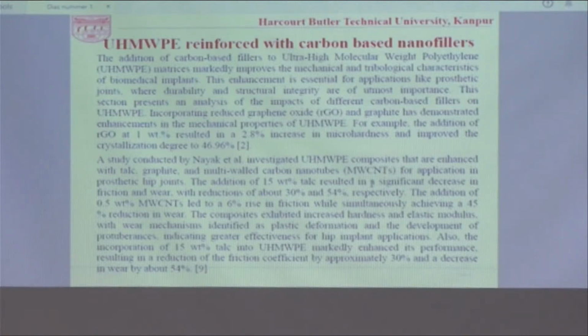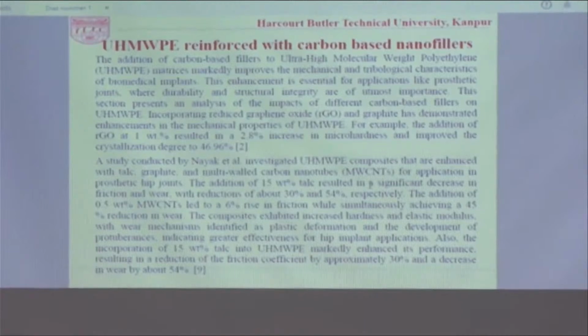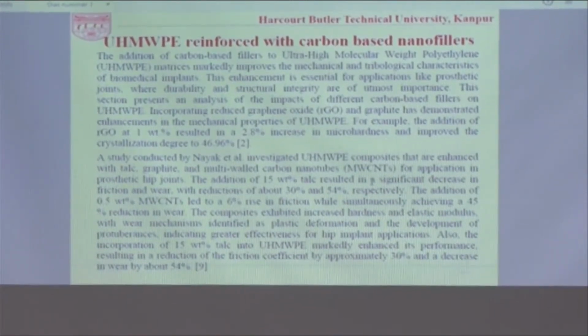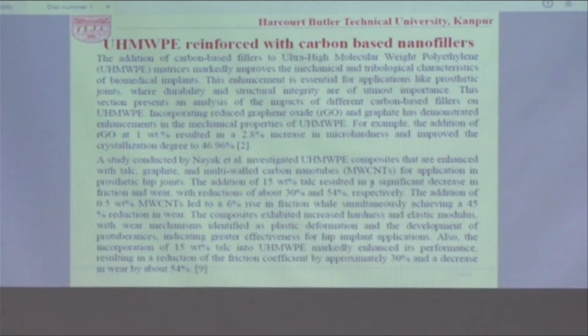A study conducted by Nayak investigated that when MWCNT, talc, and graphite are incorporated within the UHMWPE polymer matrix, the mechanical as well as tribological characteristics improved. With the addition of 15% of talc, there is a decrease in the friction and the wear of the developed biomaterials. Also, with the incorporation of multi-walled carbon nanotubes, the tribological property has improved a lot. Because of the layer by layer form of the carbon nanomaterials, it shows a lubricating property, which is essential for the articulating surface which we are going to develop.